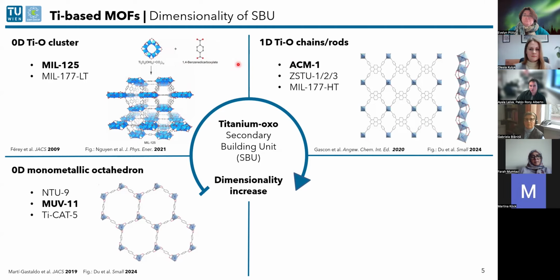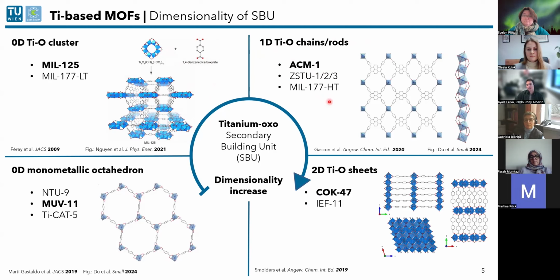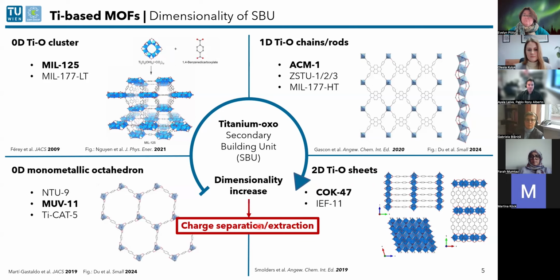We can extend this further to 1D infinite titanium oxo chains or rods, as it has been exemplified in some works, for example, ACM-1 and a few others. And one can take this even to the next step and increase the dimensionality to 2D, and the result is some titanium oxo sheets that look somewhat like this, and there are some exemplary MOFs here. So why are we interested in this? Because some have reported that this increase in dimensionality of the SBU can help in charge separation and extraction.